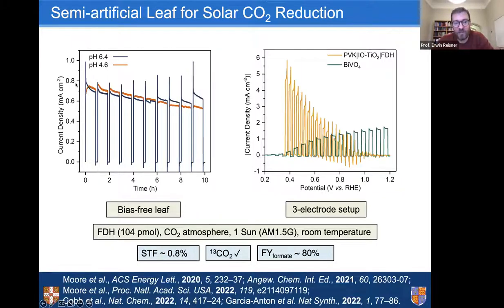But I also want to point out that these enzymes can actually sustain quite high current densities. When we started working on enzyme photoelectrochemical systems maybe 10 years ago, I would have thought 1 milliamp per square centimeter maybe an upper limit. But indeed, under certain conditions, which I won't discuss in detail, we can already go to 5 milliamps and approach 10 milliamps per square centimeter, which means in principle, if we get the device right, the enzymes would not hold us back in reaching 10% efficiency in such systems. Again, we are not there because the stack is not designed to do this, but in terms of enzyme catalysis, the efficiencies can get quite high.